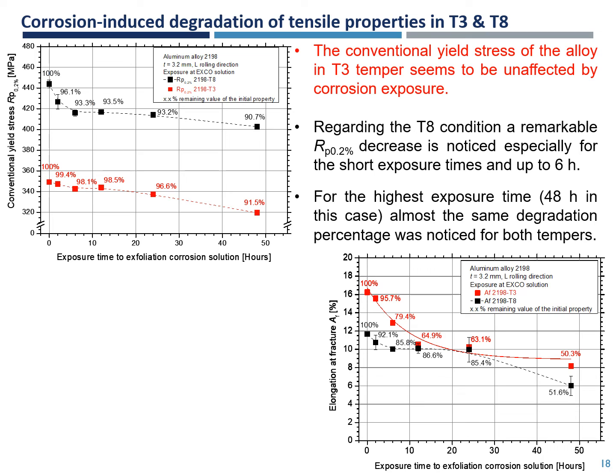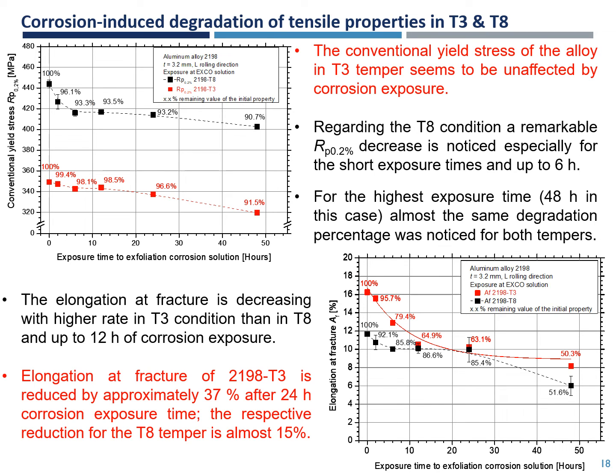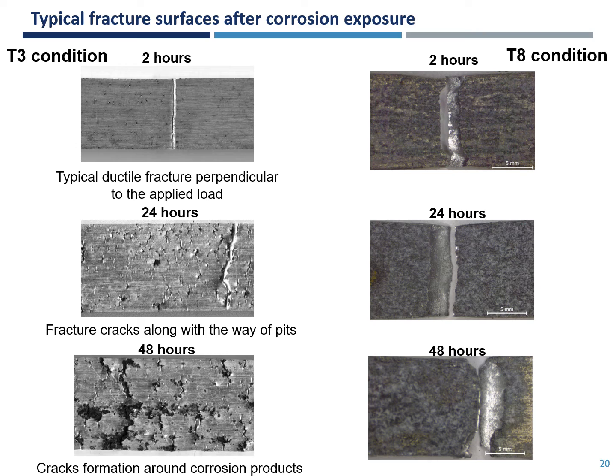Regarding elongation fracture, the elongation fracture is decreasing with higher rate in T3 condition than in T8 and up to 12 hours of corrosion exposure. Elongation fracture of 2198 in T3 condition is reduced by approximately 37% after 24 hours corrosion exposure time. The respective reduction for the T8 temper is almost 15%.